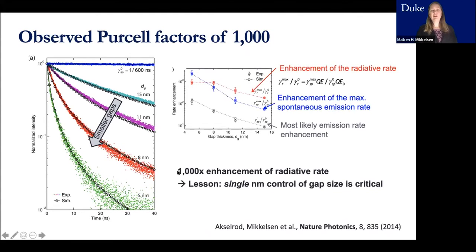And it allows us to then, from this data, extract the most likely emission rate enhancement at the different gap thicknesses here, which is shown in gray, as well as the enhancement in the maximum spontaneous emission rate, and also the enhancement of the radiative rate, which is the enhancement in the spontaneous emission rate times any change in the quantum efficiency, which I think is probably the most important figure of merit, and gives us enhancement around a factor of 1,000. So I think we have two takeaway messages here.